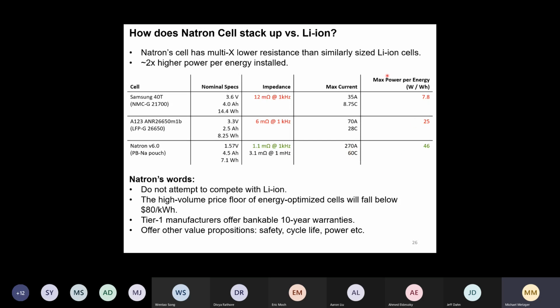And then they plot this metric here, max power per energy. So it's the watts of power you get per watt hours of energy in the cell. And here we can see that the Natron cell really stands out, even compared to an LFP cell. So they don't attempt to compete with lithium ion. I mean, they just can't reach the energy density. And also lithium ion is getting cheaper and cheaper. Here they write about $80 per kilowatt hour, maybe at some point. But their value proposition is really that these cells are incredibly safe. They provide a very long cycle life and high power.